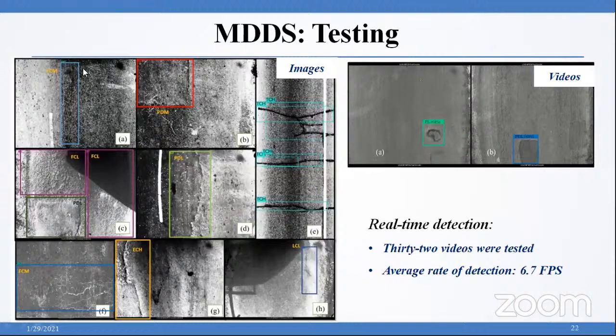When the image shown in the top left corner was tested, the system detected that the image has fatigue cracking with medium severity present in it. And this image was coming from dataset L. When this image was tested on the system, it detected that multiple transverse cracks of high severity were present. And then we also tried testing the system with RGB images.